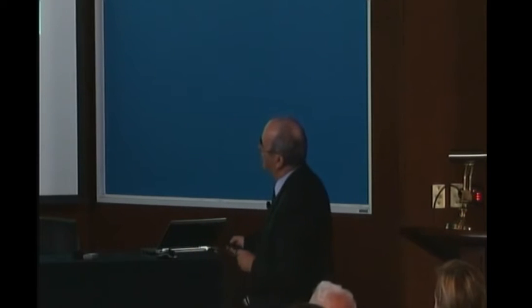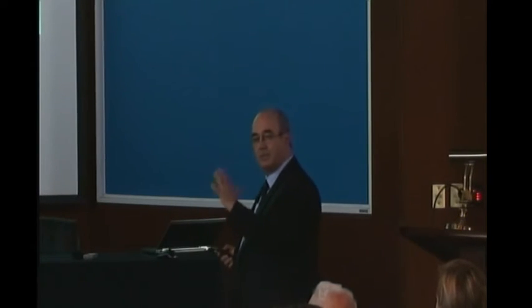This is the recent work we did in Toulouse by Dolores Manrique. She is the Mexican PhD student in the group. We tried to combine the actuation and the color change. You see here, when we change our temperature in this form, you have your actuation, and because you have the spin crossover, you also have the change of the color. You see, pink to yellow, pink to yellow. So you have two positions, mechanically speaking, and you have two colors.